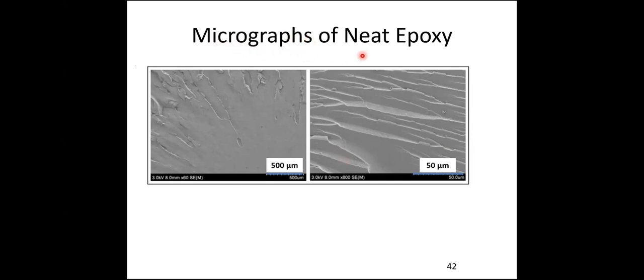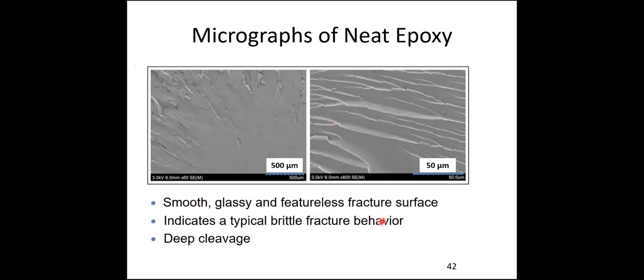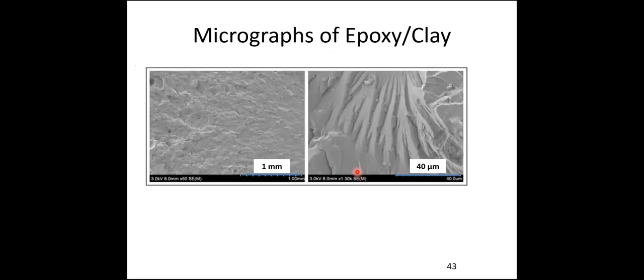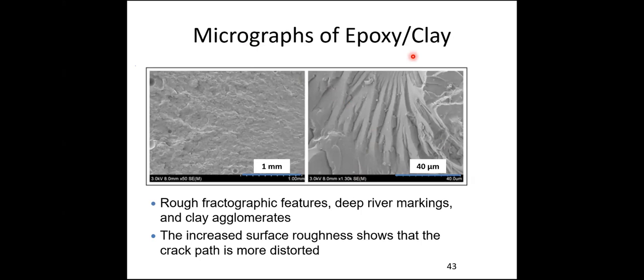So this is a micrograph of neat epoxy. One can see a smooth, glassy, and featureless fracture surface. This is a typical surface of a brittle material. Now this is the micrograph of epoxy clay. You can see rough fractographic features and deep river markings. Again, you can also see some clay agglomerations. So this is what we got from the epoxy clay composites.